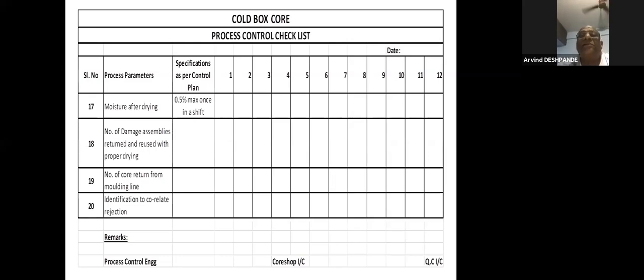These are practically seen especially on high pressure molding lines. Normally we pour metal per heat, and the number of boxes is fixed. If a core is damaged, to maintain that metallurgical control, core assemblies may come back, 2 or 5 in a day. So we cannot reject the core, but this system has to be there so that whenever any reaction comes we can correlate the rejection. The assembly is reused, rebaked, and used after so many hours. If rejection of especially core scab or blow comes, then we can correlate it.